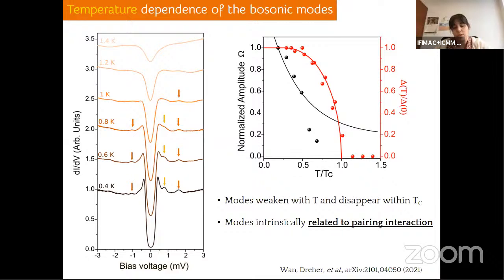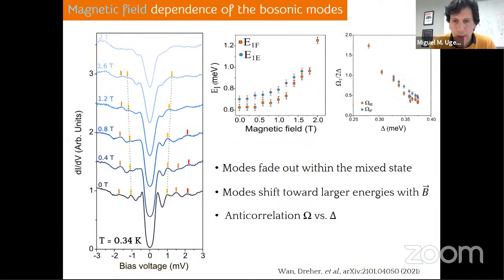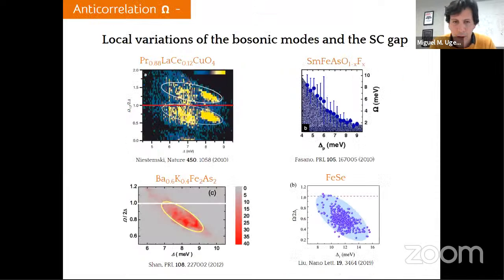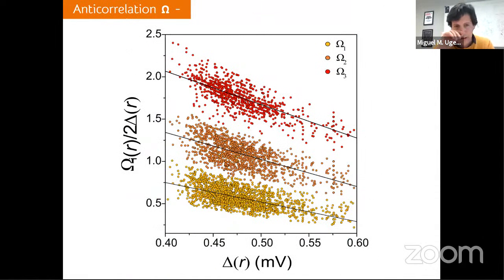And what do you think is the origin of the spatial changes of the superconducting gap in your sample? Well, they are quite small, actually. We have had a hard time plotting this because, in general, it's quite homogeneous, in particular using the samples that we use. Most of the points lie here within less than 0.1 millielectron volt.